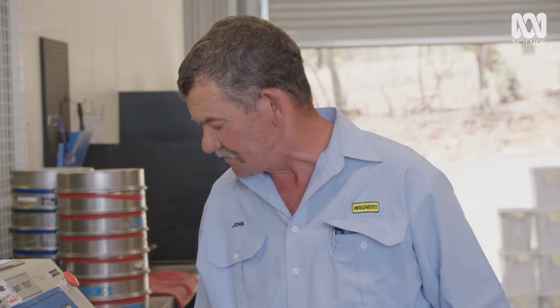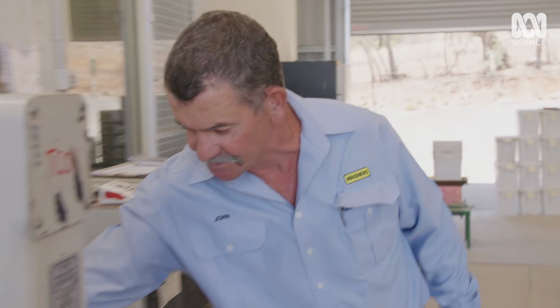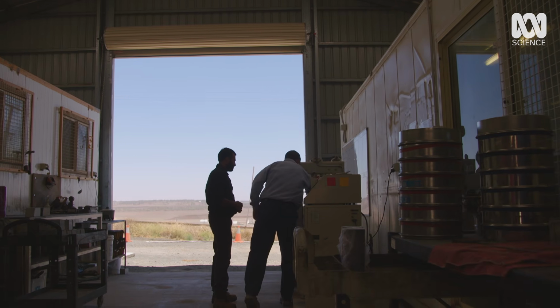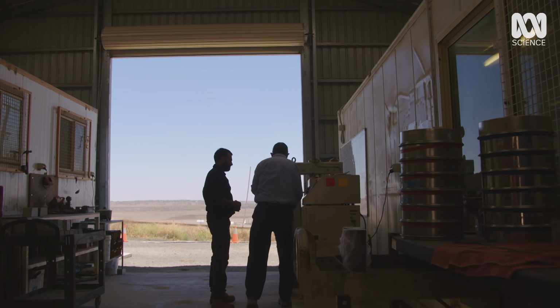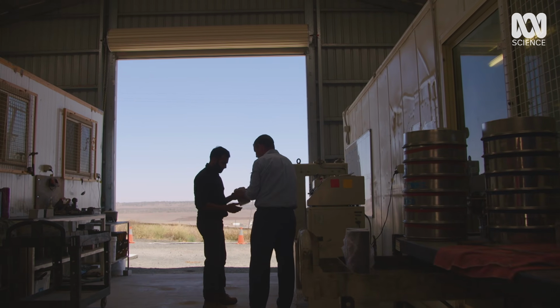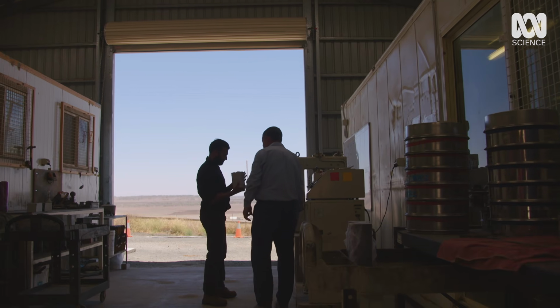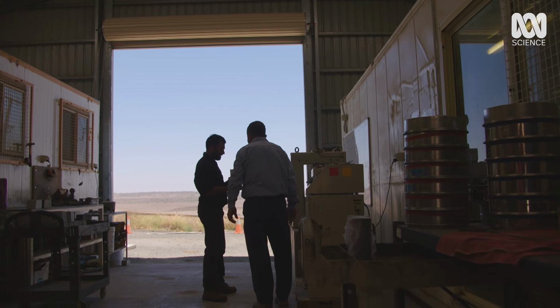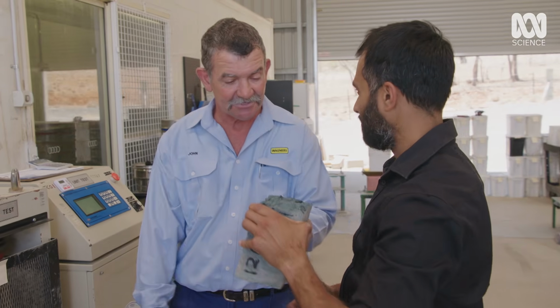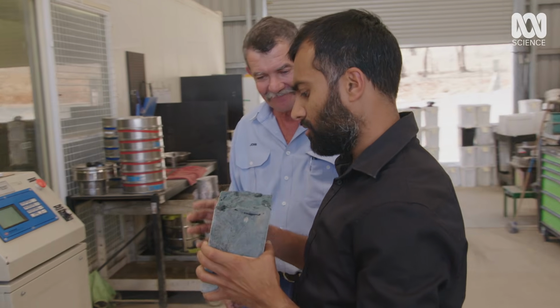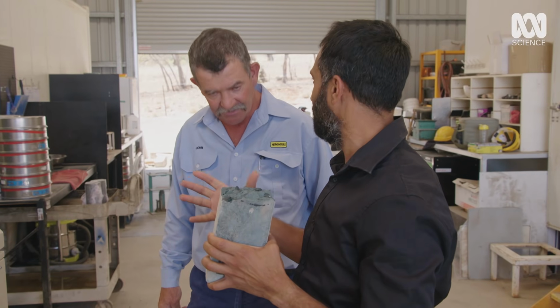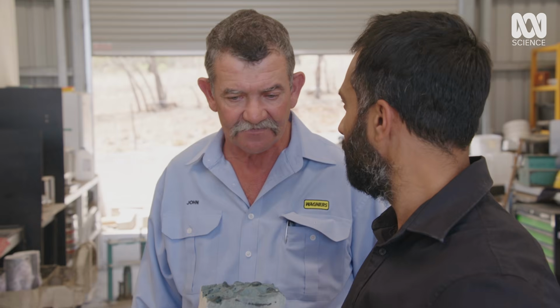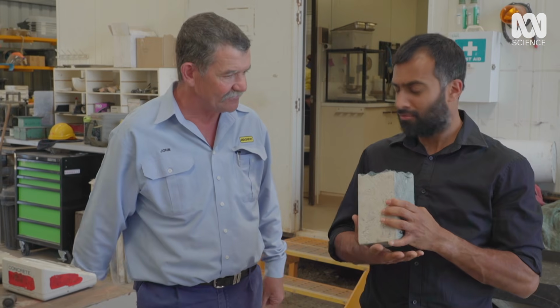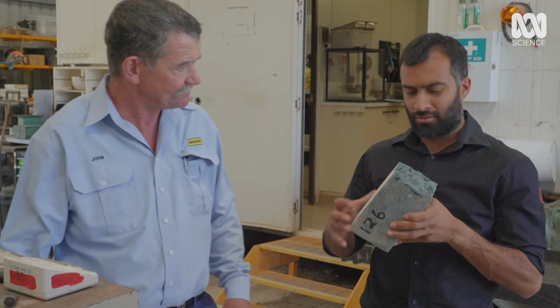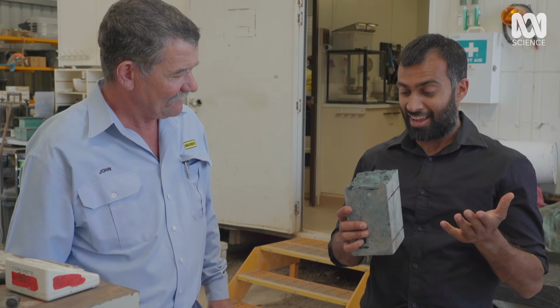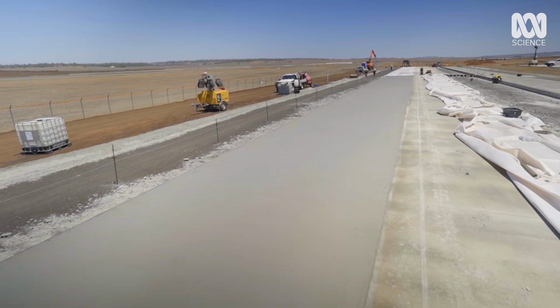So peak stress, just about 6 MPa flexural strength, which is about 20% higher than it needs to be at only 5 days of age. 6 MPa is equal to more than 600 tonnes of force per square metre. A lot more than a fully loaded 747. So this is stronger than it needs to be under the standard? It's already exceeded by approximately 20%, the 28-day requirement at 5 days of age. So it's greener, faster and stronger? Correct.